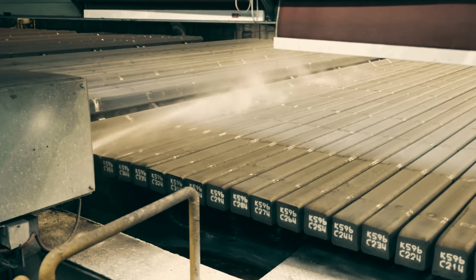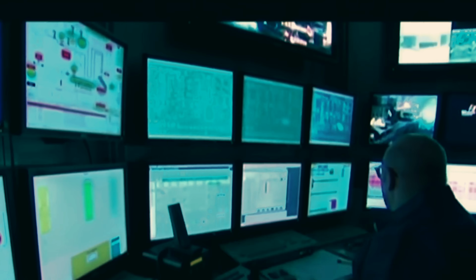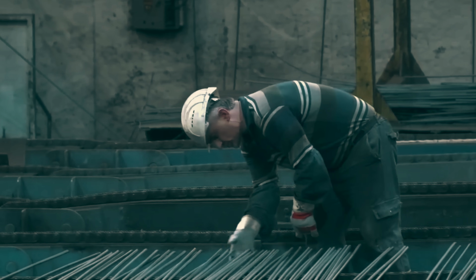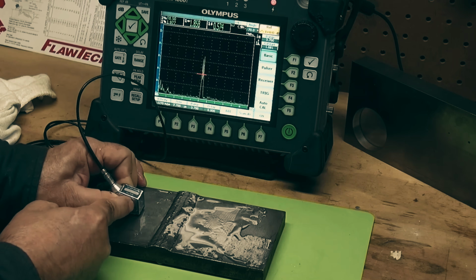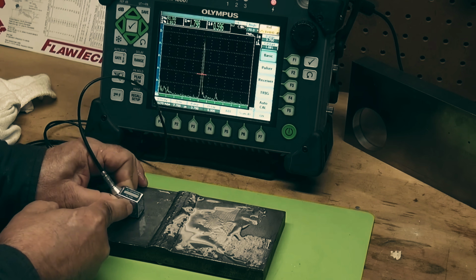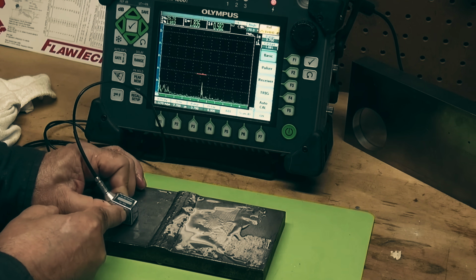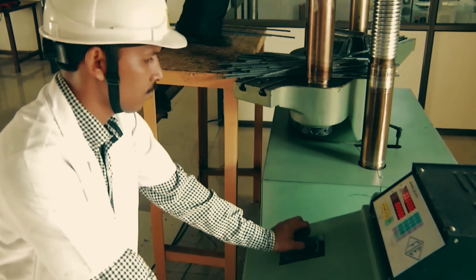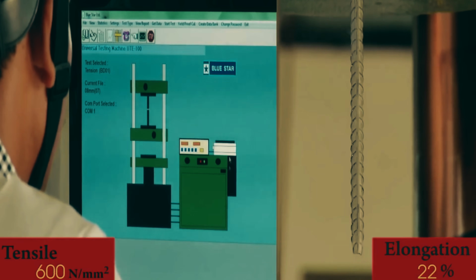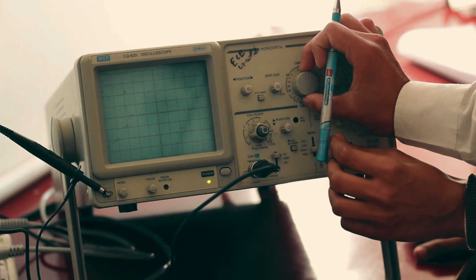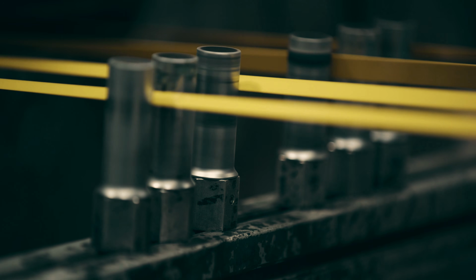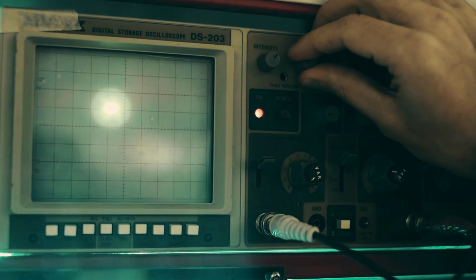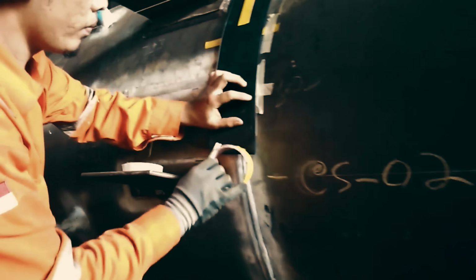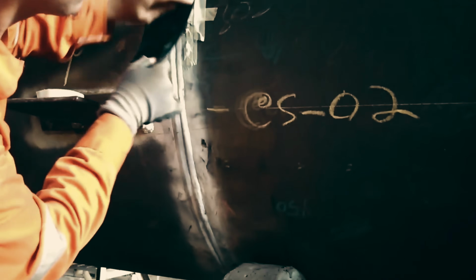Before any batch leaves the mill, samples are pulled and tested for tensile strength, hardness, and chemical composition, often by physically pulling a sample bar apart in a machine until it snaps, just to confirm exactly how much force it can withstand before failing. Sensors along the production line also scan for internal cracks or inconsistencies invisible to the naked eye, using techniques like ultrasonic testing, which sends sound waves through the metal and listens for how they bounce back. Any hidden void or crack reflects the sound differently than solid steel does, flagging a defect long before it would ever be visible to a human eye.